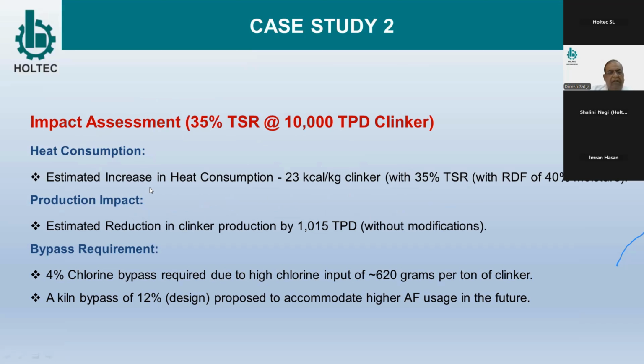We estimated that heat consumption is expected to increase by 23 kilocalories because of the high moisture of 40% in RDF. Production was impacted, with around a 1,000 ton per day reduction in clinker capacity if we don't make modifications in the system. So this was the expected reduction, which was quite significant.